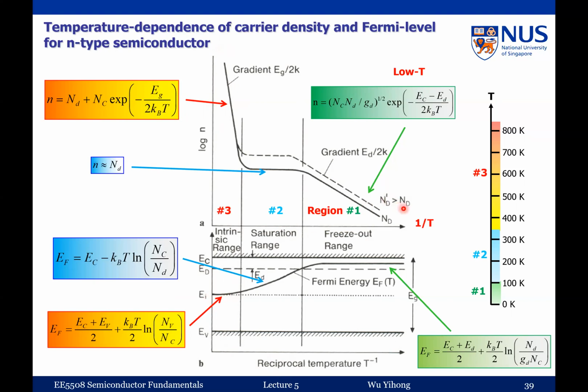Okay, and if you look at the electron density within this range, we found it earlier. If you forgot about this, you can go back and check the previous slides. If we take a log of this and plot it as a function of 1 over T, you get a slope. The slope is given by EC minus ED divided by 2KB, and of course it's negative, which is why you get a straight line here, right? The gradient is roughly given by ED over 2K. Here ED is the dopant energy level, and here ET is the ionization energy, right?